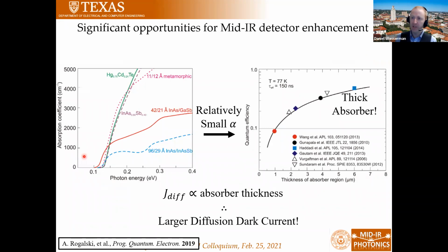Now, the real opportunities in my mind here are for mid-infrared detector development. The reason for this is the type 2 superlattices are sort of the hot new material system for IR detectors, but there's a real problem with them. You have a lot of benefits because you can essentially separate your electrons and holes, and that allows you to control the recombination energy or the absorption, the band edge essentially of this material. But by separating your electrons and holes, you've effectively decreased the optical dipole and you've made them less efficient absorbers, right?